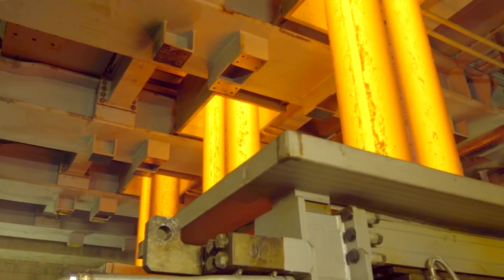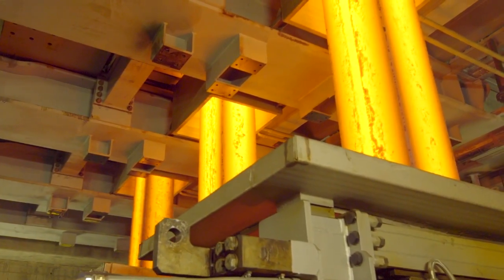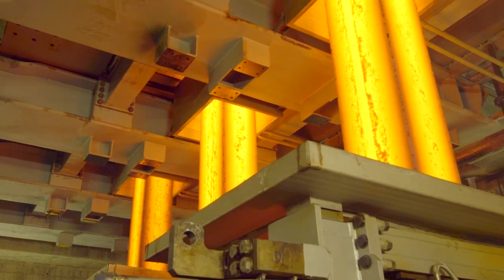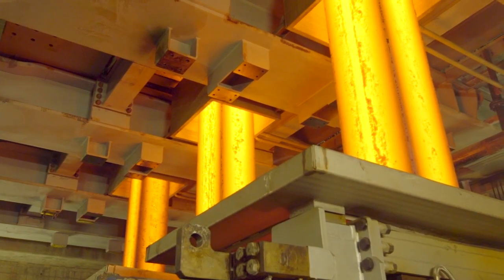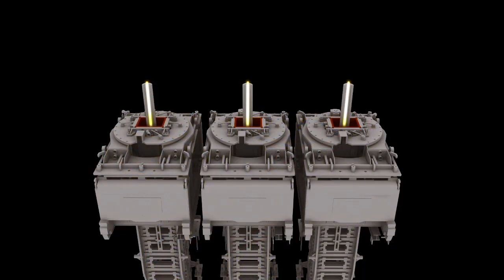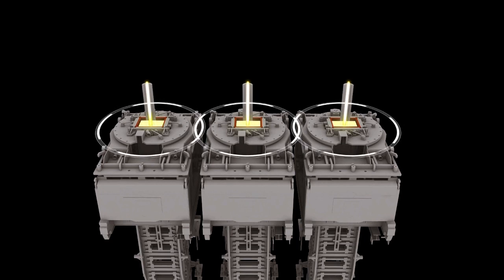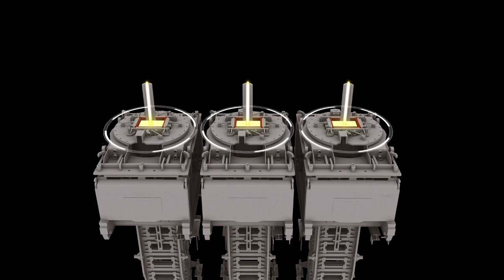We use refractory stopper rods to control flow from tundish to mold. The mold has a set of 4 copper plates that we clamp together and water cool. Mold powder protects the steel in the mold from oxidation. While in the mold, we utilize electromagnetic stirring to improve the solidification pattern.